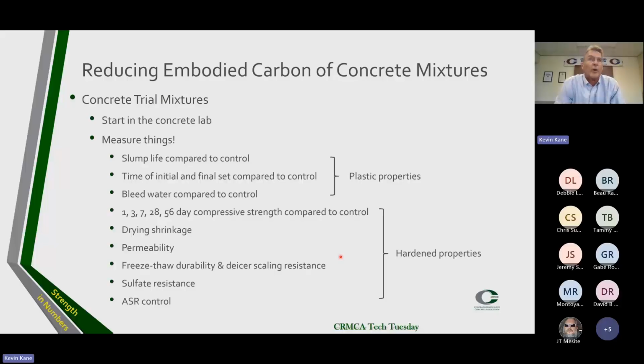Hardened concrete properties: 1, 3, 7, 28, 56 day compressive strength compared to control. Drying shrinkage, permeability, freeze-thaw durability, and de-ice scaling resistance. You've got to measure these things. Sulfate resistance, ASR control. It's a lot of work, a lot of time, especially sulfate resistance. That's not a quick test, is it? You don't get any results for 6 months. ASR is pretty quick, but sulfate resistance takes a long time. In fact, if you're going to be on S3, you've got to wait 12 months. So there's a lot of work and a lot of time that goes into it. It's a huge commitment, but you've got to be willing to do the work.